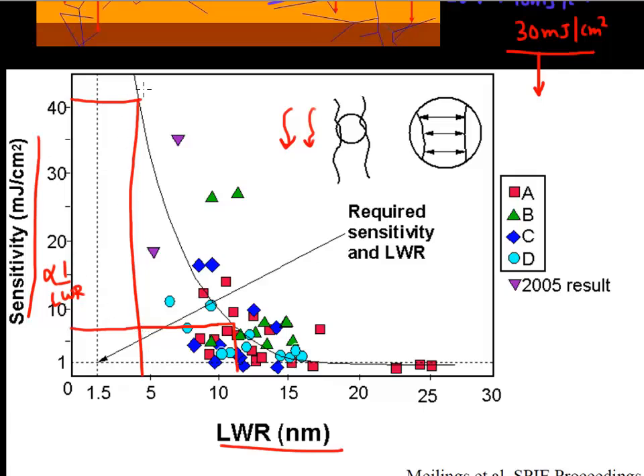As we see, that experimental data actually falls right on that inverse relationship curve. So if you have less dose required or you have a lower sensitivity for your resist, your individual photons can cause now a much higher change in your width of your pattern and you get a much higher line width roughness.